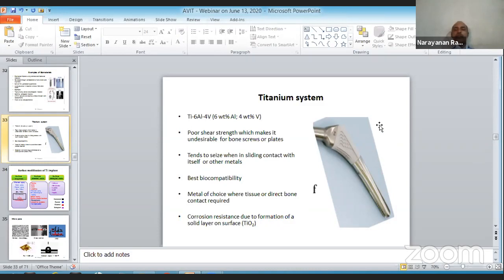The reason is, when you place a metal, and I told you it is surrounded by body fluid, which is highly corrosive. We also simulated a body fluid. What happens is this piece is basically a metallic piece, and if it contains nickel, and this nickel comes out of the implant, it has to enter the body stream. It is found that nickel is highly carcinogenic. So where does nickel come from? Nickel will enter the body stream only from here. If this implant doesn't contain nickel, then this can be ruled out.